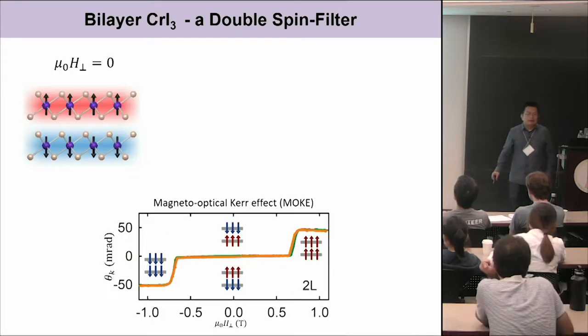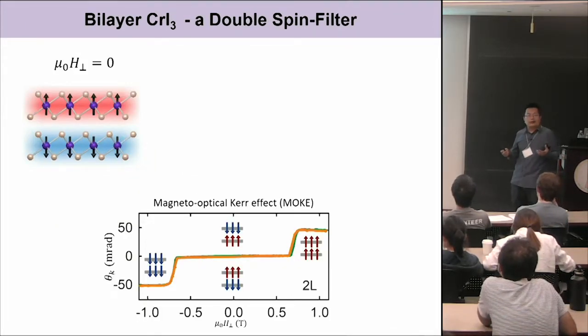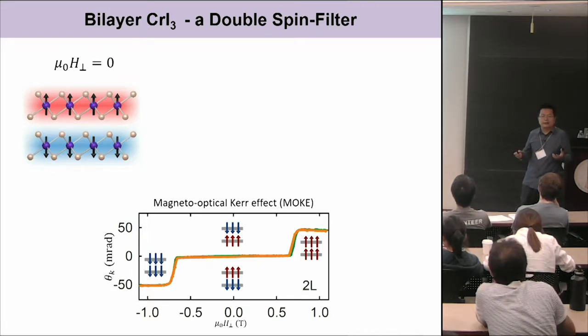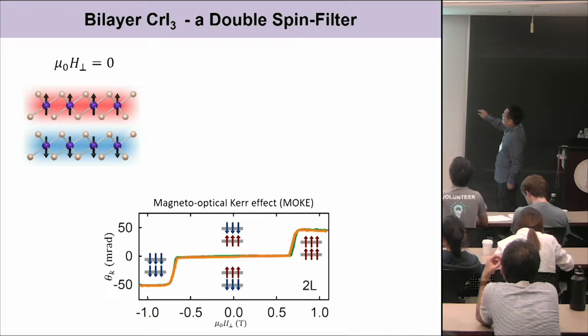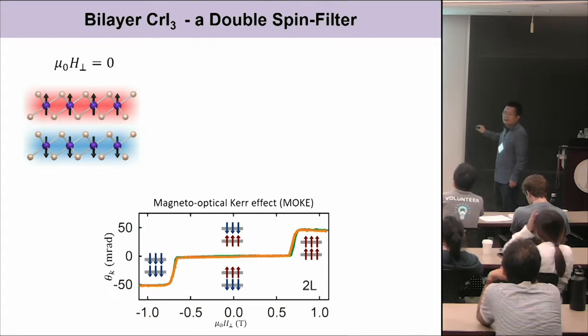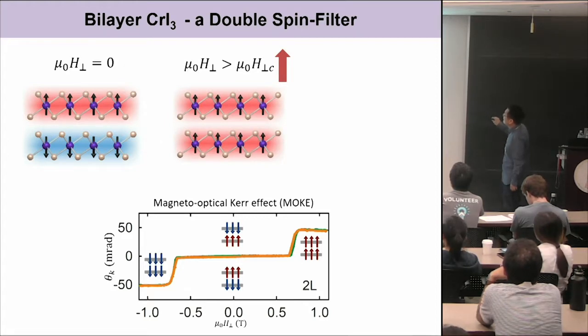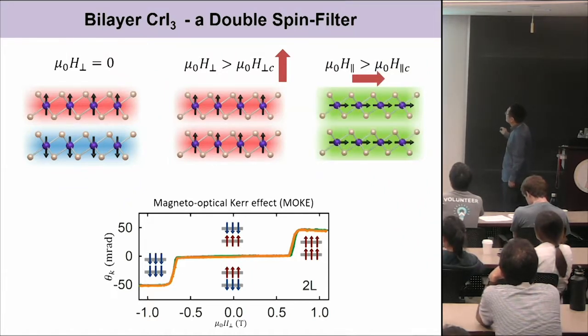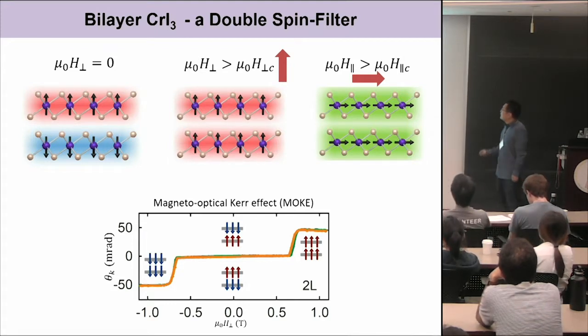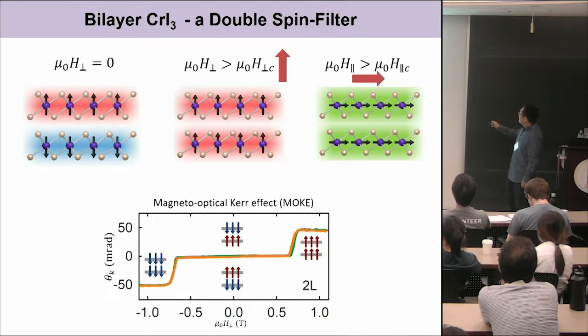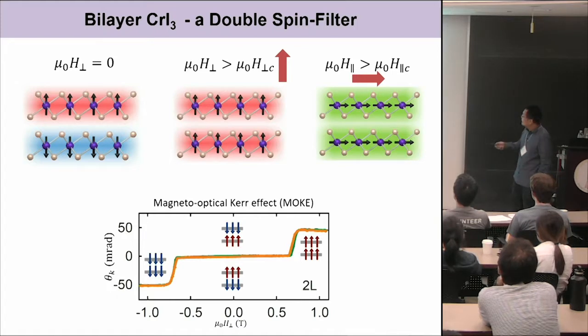And it turns out the bilayer chromium triiodide I just talked to you about is a perfect spin filter, right? The spin ground state is exactly two spin filters anti-aligned with each other, right? It's interlayer antiferromagnetically coupled. Therefore, if you pass current through the system, it will be suppressed. Then we can also apply a magnetic field to align the two spin filters in the same direction. Then the tunneling current will be increased. We can also align the spins in the horizontal direction, for example. So bilayer CrI3 is a kind of perfect system to realize these spin filter effects.